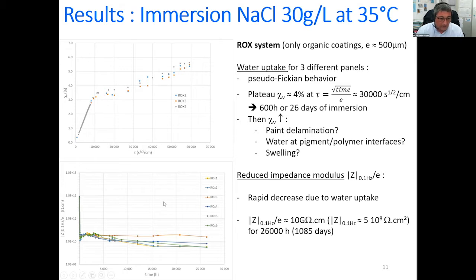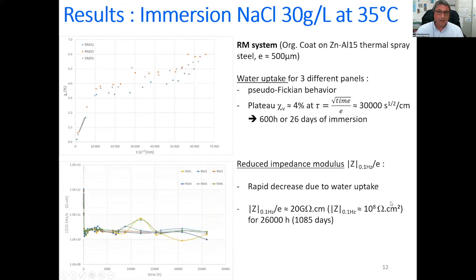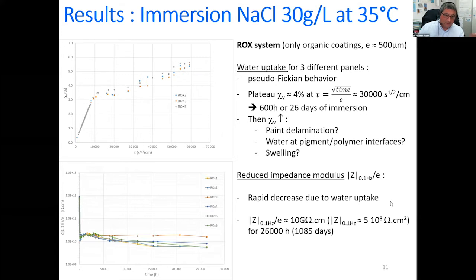We can also look at the reduced impedance modulus. As you can see, in the first hours of immersion, we have a rapid decrease. This is of course due to the water uptake, and afterwards we've got a quite constant value for this parameter for more than 1,000 days of immersion at 35 degrees C. That was for the ROX system, so it means only organic coatings applied onto the steel.